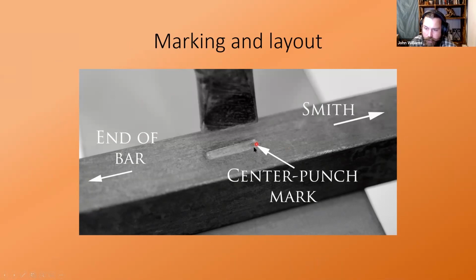The slot punch itself will be about 1/8 inch thick, and it will be about 7/8 inch long. That matches your through and through drift approximately. You're going to punch with the heel of the slot punch on the dot.